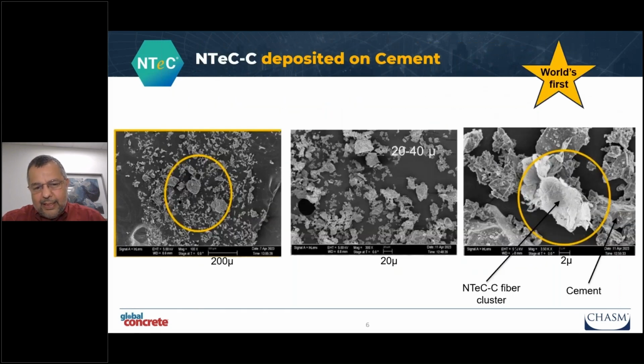Now, if I take the case of directly depositing on cement, how does it look at a microscopic level? At a microscopic level, what you see is clusters of nanotubes attached to cement, and you'll never find a free nanotube, because the good thing about nanotubes is they want to stick to things. The good and bad thing is they want to stick to each other, but as long as you can fibrillate them and make them stick to cement, they'll stick to cement forever. It's in fact impossible to get them apart.